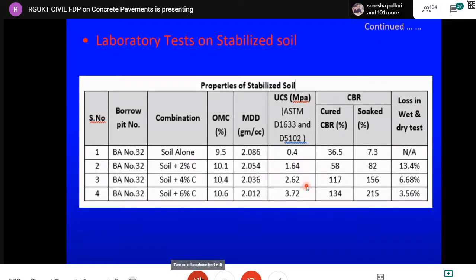In the previous slide we have seen that the minimum UCS value should be 1.5. With 1.5 on the stabilized soil, we can go for the granular layer with cement-treated granular layer. That is one of the options given in the IRC SP 62. So in this case, even with 2% of the cement itself, we got 1.64 as the unconfined compression strength value. So I can straight away say that we can directly use 2% of the cement for construction of the stabilized layer.